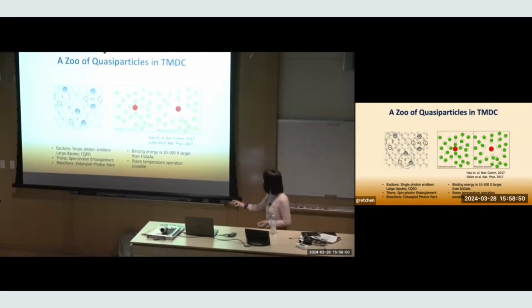This topic has all been studied in good old gallium arsenide, indium gallium arsenide, semiconductor quantum wells or quantum dots. But now they're being restudied in these materials because they have a very stable, large binding energy, so they become stable at room temperature. And when you dope the material and shine light to create an electron hole pair, you need to worry about whether this electron hole pair is interacting with the entire Fermi sea, and then you have a more complicated situation. But I'll skip that for the purpose of this talk. All of these transitions lead to a prominent resonance in the light emission or absorption spectrum, and they are stable at room temperature. I'm going to tell you how these transitions get modified when I build an even more complicated structure.